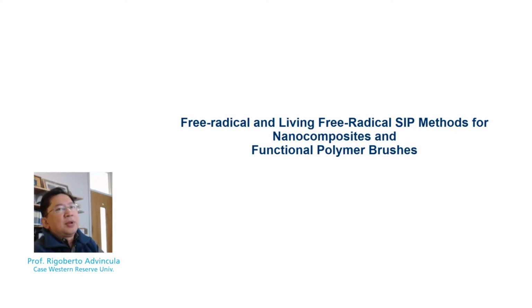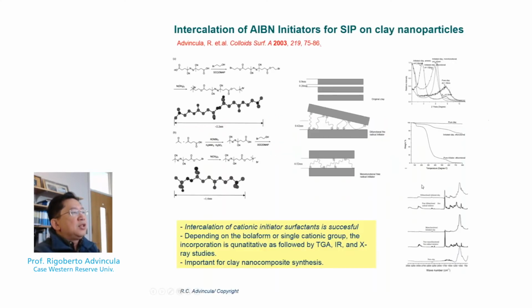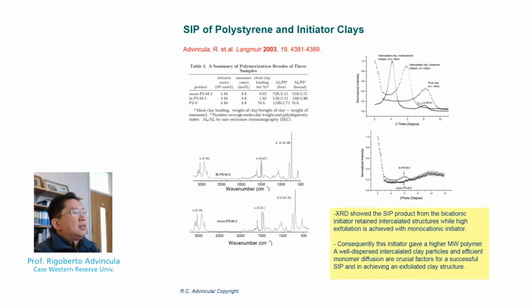Now let me switch to free radical polymerization, where we have utilized AIBN-like initiators as shown here, and then grafted them on the surface and did the polymerization at the same time. In this particular design, we have an AIBN-like initiator with two quaternary amine groups. These were inserted on the nanoclays, and during the polymerization, they also produce delamination. Again, we follow this by infrared spectroscopy, X-ray, and also thermogravimetric analysis. The bottom line is that the grafting by free radical polymerization of polymers on clay nanoparticles can be easily achieved by these procedures.